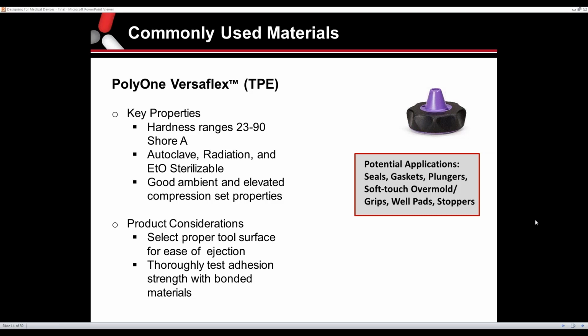But John and Glenn, I know you guys probably have something to add about processing of this material. It can be a little tricky, right? Yeah, you definitely need some overmolding expertise, and as you said, the adhesion factor. You have to make sure you're overmolding this material to the proper substrate material. Make sure your surface finish on the tool is correct for the ejection process. Really, just making sure the two materials match as far as the adhesion goes.